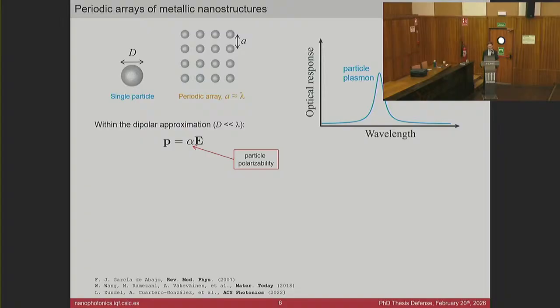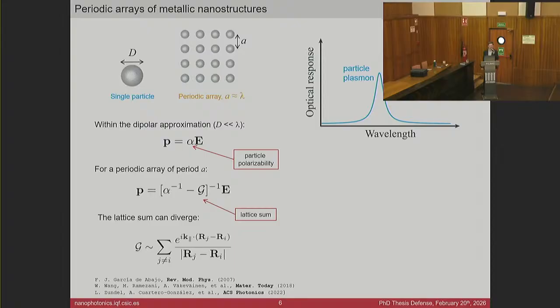we now have to modify this expression here, because we have to take into account the interactions, giving rise to this slightly different expression where we have the response of the individual nanostructures, but also their interactions through this term that we call the lattice sum. This lattice sum, we can understand it as a sum, an infinite sum in principle in a periodic array, over the scattered waves by each element that is spread through this sum, where I keep here only the far field component of the scattered wave, which is going to give us very interesting effects, especially when these terms are in phase, because then all of the terms will add up constructively.